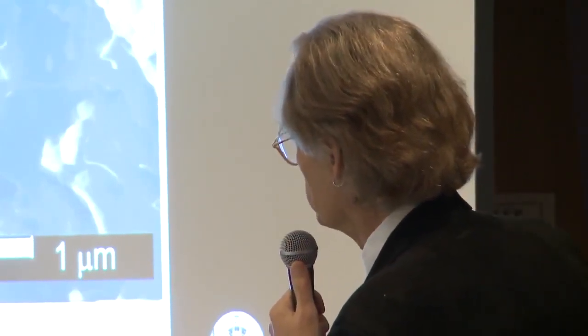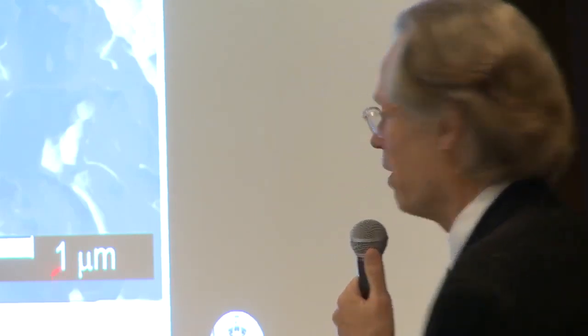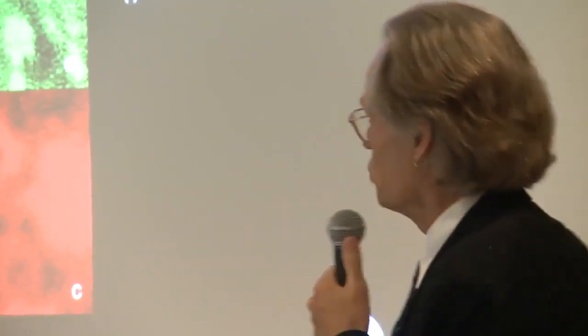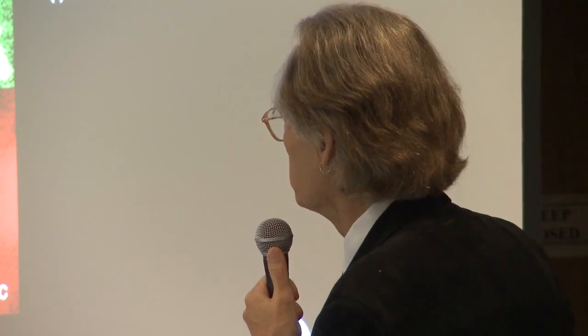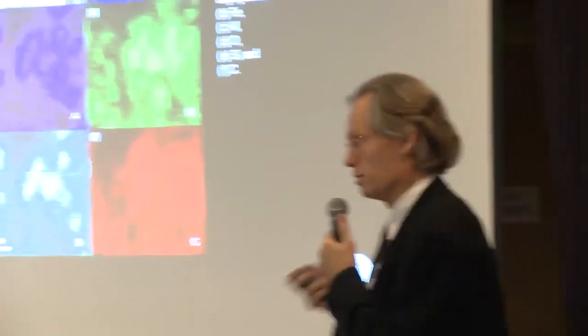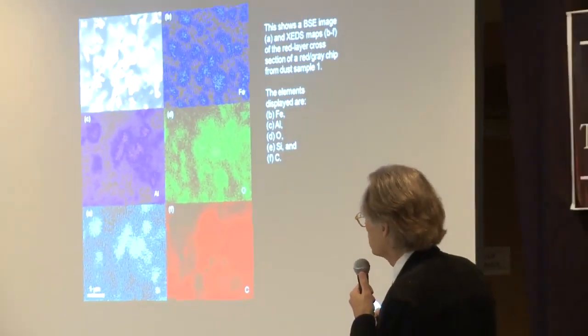You see here the magnification is 50,000. This is 1 micrometer. This is 1/1000th of a millimeter. Further information we get if we apply this energy dispersive spectroscopy to a close-up of the red phase. This is an electron microscope. This picture shows where the iron is. This picture shows where the aluminum is, and where the oxygen is, where the silicon is, and where the carbon is. And there is some correlation. You can, for instance, see here that the aluminum is found in the same regions as the silicon, and we may already get the impression that the aluminum and the silicon are located in these flat,